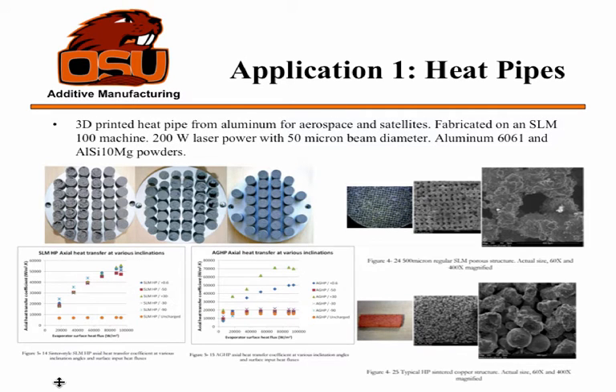From what I was reading, and I don't know if this is true, it's really hard to make a sintered porous aluminum because of some of its sintering properties. It tends to wet and then agglomerate and make a solid structure rather than a porous structure. So that's one advantage that they have. Thermacore does not make an aluminum sintered wick in any other way, but they will make copper wicks, which is kind of hard to see, but it's down on the far right. You can see the traditional copper versus the aluminum structure, which is the lattice structure wicks.